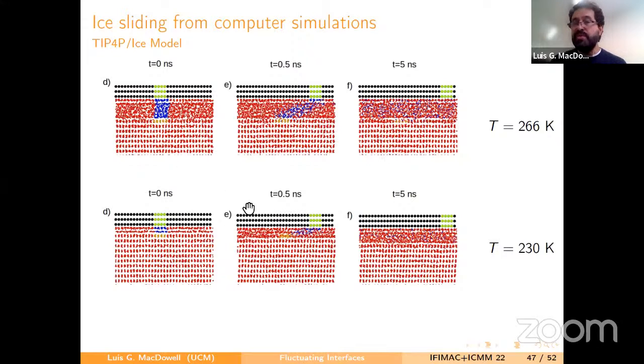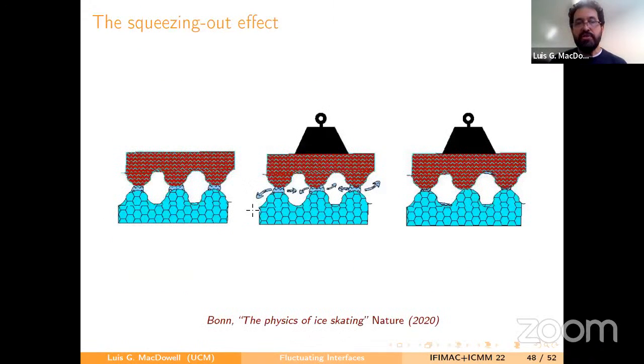Okay, so to summarize, well, no, not to summarize. All of these simulations were performed just at 1 bar pressure, which is very low. And so experts in tribology, and there was a recent paper by Daniel Bonn in Nature, would argue that because of the asperities, the pressure on the asperities is much larger than 1 atmosphere. And it's a well-known phenomenon in tribology that when the pressure is very large, then the lubricating film is being squeezed out. And that's why water is a bad lubricant usually.